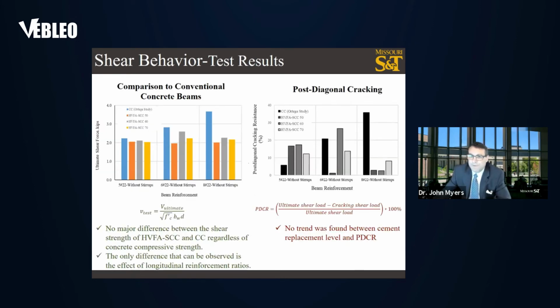To provide further verification on the results of the high volume fly ash SCC shear study, the results of the present study were compared to shear behavior study conducted by Carlos Ortega. And here you can see the comparison to the Ortega study of the conventional concrete as well as the HVFA-SCC. There is no major difference between the shear strength of the high volume fly ash SCC and the conventional concrete regardless of the concrete compressive strength.